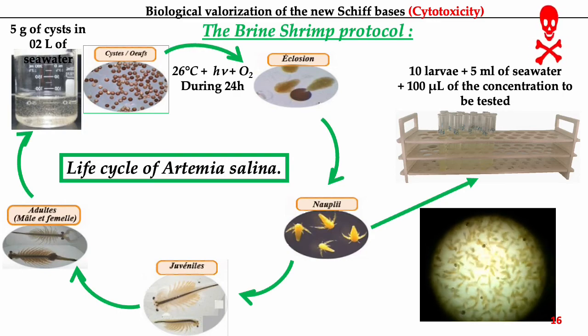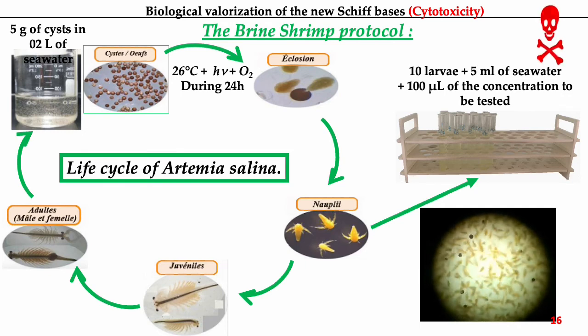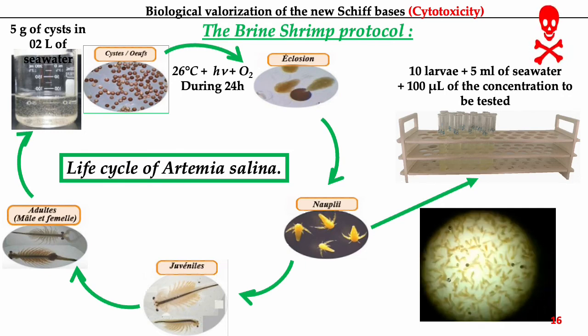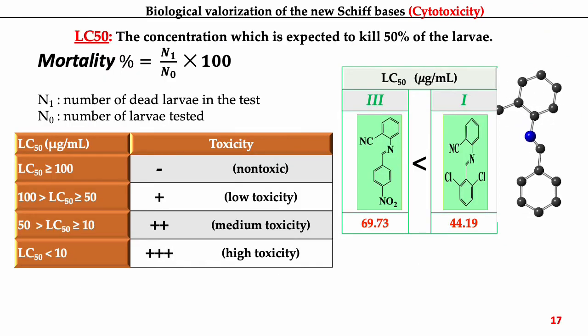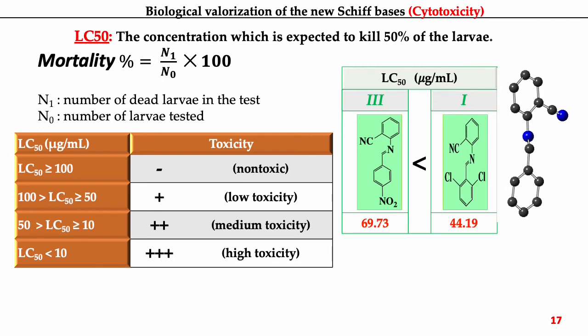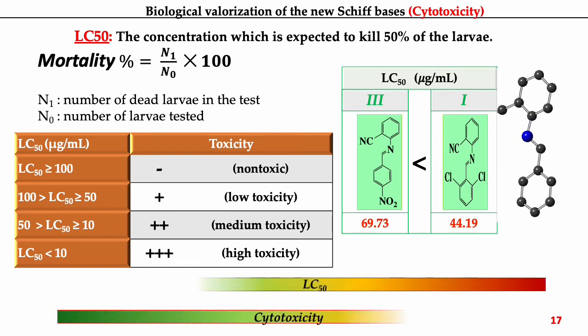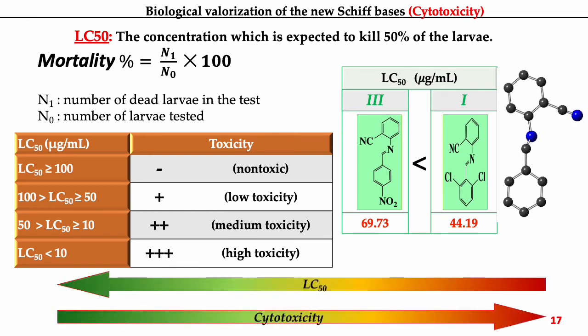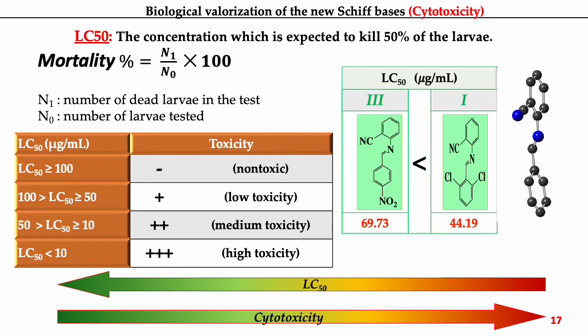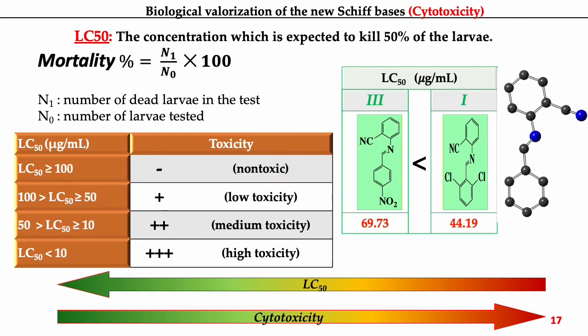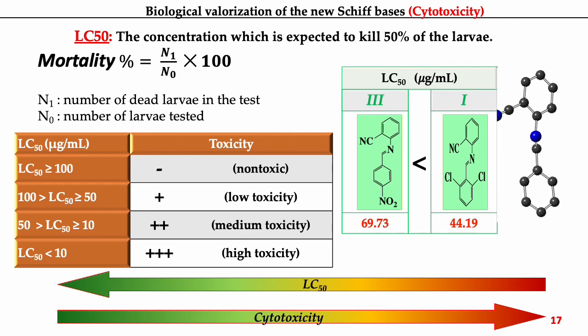The other biological test carried out for our compounds is the in vitro cytotoxicity. This test was carried out using Artemia salina larvae. To study the concentration-mortality relationship, we often use the lethal concentration, which causes the death of 50% of the larvae. LC50 is inversely proportional to the cytotoxic property. The degree of toxicity of our Schiff bases was evaluated from this table and indicates that compound 1, with an LC50 of 44.19 microgram per milliliter, is more toxic than compound 3.